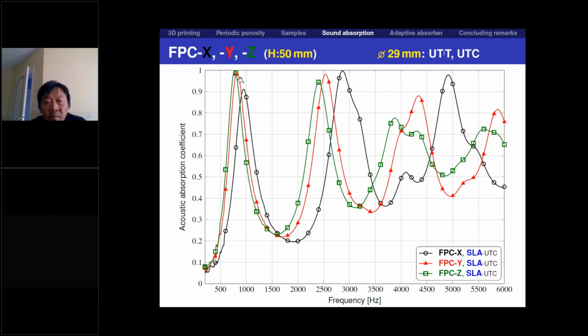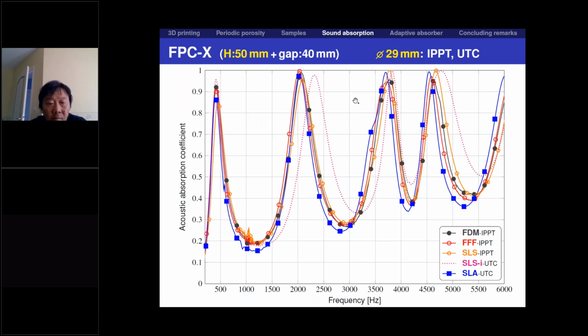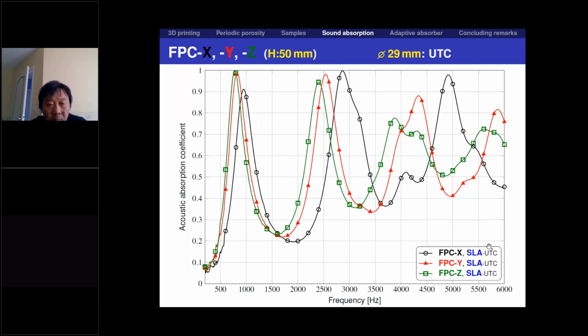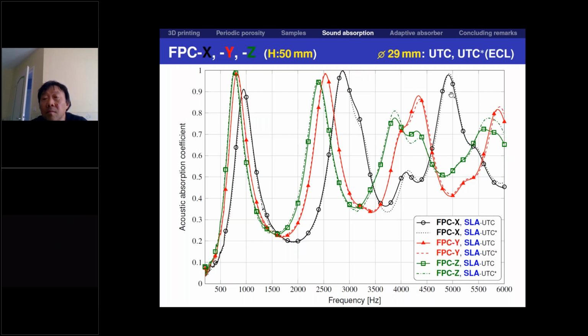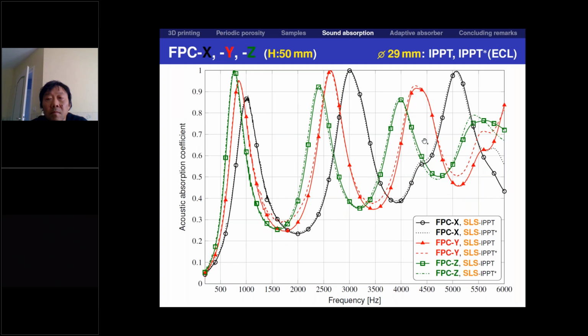Finally, the results for other orientations, because these were only for FPCX samples. These are the black resin samples from France, from UTC, and I asked Nicolas to send their samples to École Centrale de Lyon, and they measured this, so you see that the acoustical measurements are correct. I did the same with my samples, and here you may see that my measurements were also done correctly. It is important to mention here that I manufactured and measured my samples in early spring, and in École Centrale de Lyon they did the measurements in July.